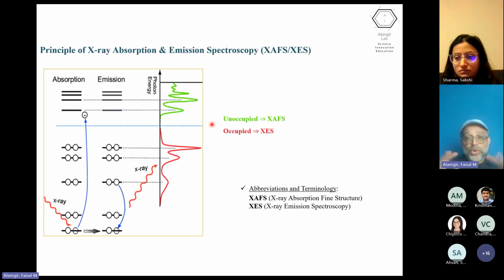So let's take a moment to go through some description of X-ray absorption and X-ray emission, so that those of you who are not familiar with these techniques can get an idea. Quite simply, both of these, as I said, are core hole methods, and the core hole is generated by an external X-ray source to begin with. So X-ray from the outside is coming in, and has to have the threshold energy to knock out a core electron. And once that happens, what you're left behind with is a core hole, and that's why this is called a core hole method. The electron that is released has several options depending on the amount of energy it has.